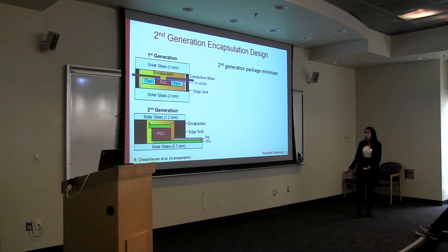So I propose a second generation package design, as shown here, to fix the three problems I mentioned in the previous slides. First, I tried to fix the metal-induced degradation problem by using a top ITO electrode here. In this case, as you can see, there's no vertical overlap between the metal and the perovskite. So this metal cannot get to the perovskite, and we shouldn't have the metal-induced degradation problem.